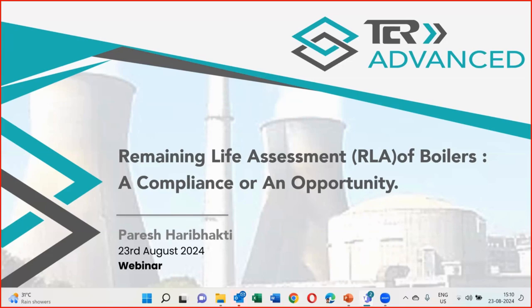So I thought, let me talk on those lines and provide the viewpoint. The regulatory authorities have asked us to do remaining life assessment under the Indian Boiler Regulation Act. They have indicated that any boiler operating at more than 400 degrees centigrade needs to be subjected to RLA after 11 years of operation. Boilers operating below 400 degrees centigrade can do RLA after 25 years of operation. Then you can do re-RLA depending upon the condition, but normally 6 and 12 years are provided for re-RLA service. However, there is a compulsory inspection which has to be done every 2 years.